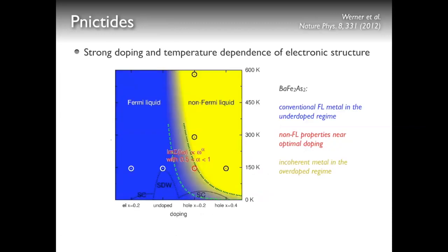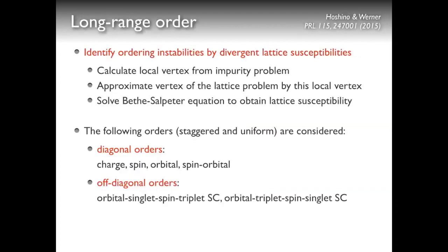We also did at some point some simulations of pnictides, and this is a phase diagram in the space of filling and temperature. And you can see that for this barium 122 compound in the undoped sample, we are in the Fermi-liquid regime. And then as we hole-dope the system and move towards the half-filled d shell, we quickly move into this frozen moment regime. And interestingly, the crossover with the square root self-energy occurs roughly at the hole doping where superconductivity appears at low temperature.